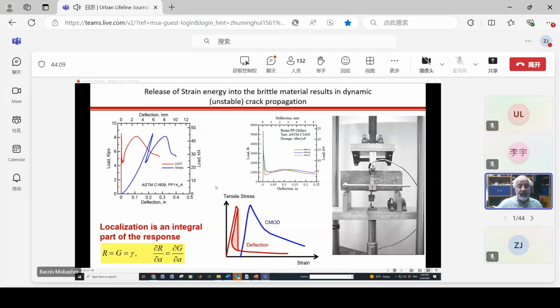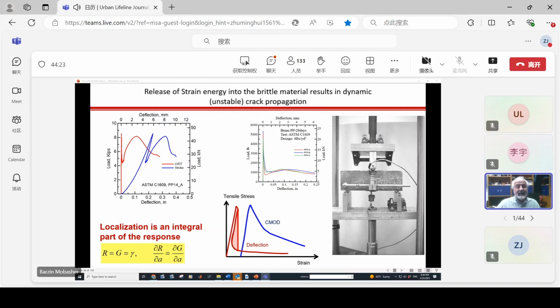So another parameter that we need to look at when I talked about energy dissipation is the manner in which we test. When we test materials, depending on whether we do closed loop control or deflection control or load control, that affects the way the sample behaves. And the best way of looking at it is to run a test that's CMOD controlled. So we put a notch and load it, we get this blue curve. But the similar specimen, if I test it under deflection control, when the load is applied under a constant deflection measured by the LVDT, what we would see is that the response all of a sudden drops at this point. And this zone, this dashed area, is the amount of energy that's stored in the specimen that's given back to the test machine.